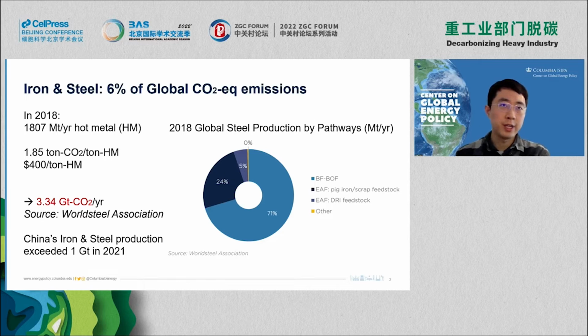In 2018, over 1.8 gigatons of steel hot metal was produced globally, and to produce that, on average, 1.85 tons of CO2 is emitted per ton of steel hot metal production, and a $400 cost is paid. That adds up to over 3 gigatons of CO2 equivalent per year, and that is the data for 2018. The most recent data shows that China is producing over half of global iron and steel, and China's production exceeded 1 gigaton alone in 2021. And that is how much iron and steel we produce globally these days.